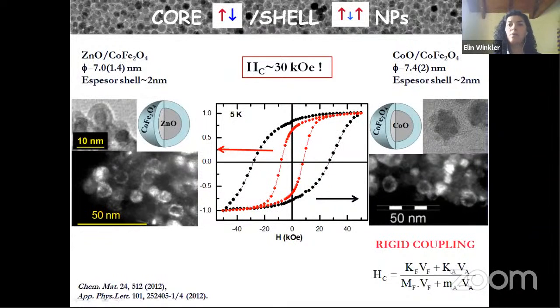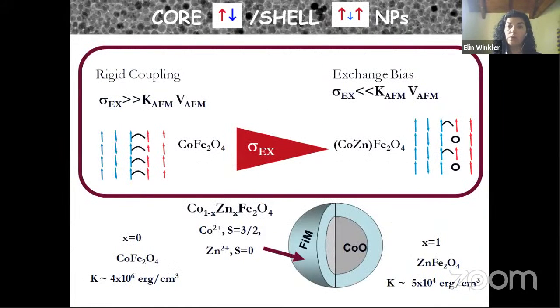So right now, when we synthesize the system, we think about how we can reduce the exchange coupling at the interface in order to move from the rigid coupling to the exchange bias regime. Well, one way to do that, here, for example, this is the antiferromagnetic material, and this is the ferromagnetic one, and this represents the exchange coupling at the interface. And one way to reduce the exchange coupling is to cut some of these bonds. And how can we do that?